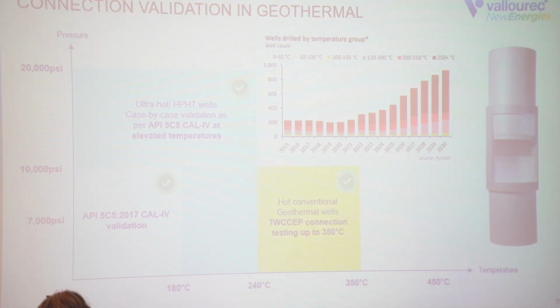So we have, again here, run some testing according to a specific protocol, which is called TWCCEP. It's a thermal well testing protocol. And the connection technology is now validated up to 350 degrees Celsius, which is enough to cover some ongoing project, but we see now more and more projects with higher temperature, targeting sometimes up to 450 and even sometimes slightly more. So we are working, this is not yet achieved, we have an R&D plan to go beyond and to test the connection technology beyond.